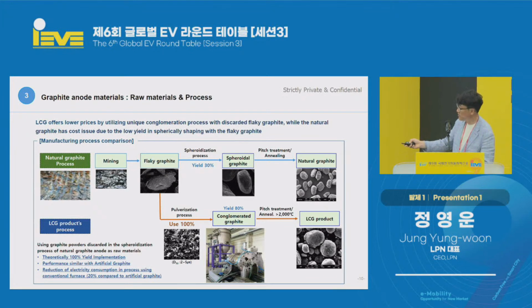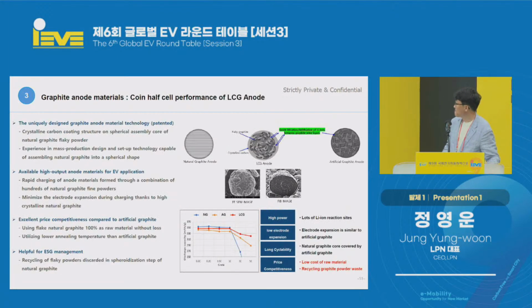After spheroidization, using the facility that we developed, we put them into spherical form, and the yield here is 80%. At first, after 4 days of processing, this is what we had for 15%. But the facility that we developed would require 10 minutes of processing, achieving 80% of yield, and the remaining 20% would be either too big or too small, and they will be pulverized again and then recycled. So the usage rate would be 100%.